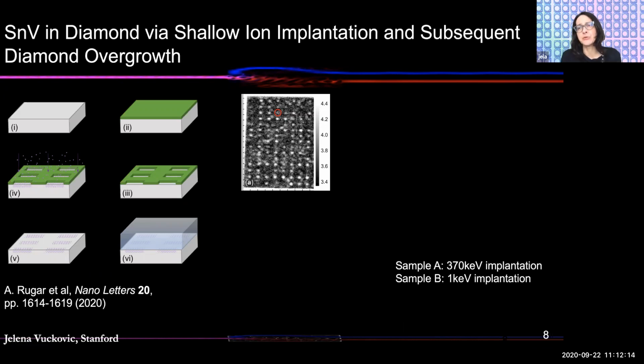And what people normally do to insert these color centers in diamond is either ion implantation or using focused ion beam, which is again ion implantation, but in a controllable way. But all of these processes have to be performed at high energies, hundreds of kilo electron volts. And that process actually damages the crystalline structure of diamond, introduces some local strain, and then lifts the inversion symmetry of the color center, which leads to its sensitivity to the environment, including first order to DC Stark